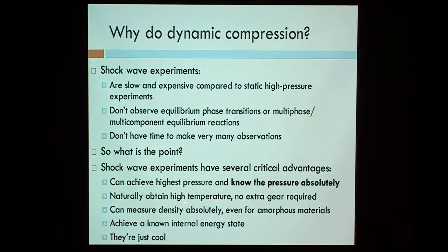It is natural when you shock a material, as it goes to high pressure, it also goes to high temperature. So you don't have to bring in extra equipment like a laser or an external heater or something to study high pressure and high temperature. In fact, you can't avoid it. Next advantage is that we know density in shock compression experiments as an absolute number from conservation of mass.